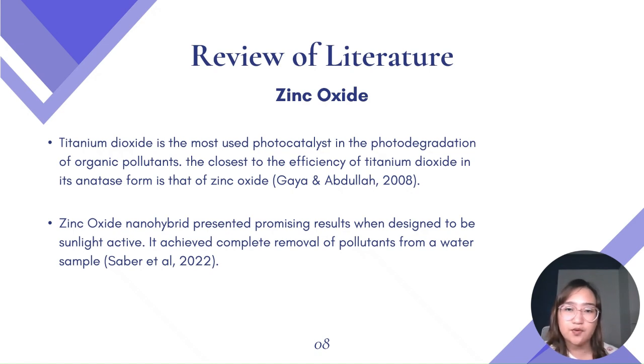Zinc oxide is observed to be of higher efficiency when its structure is crystalline and of smaller crystallite size and particle size. There are reports suggesting that the optimum size is in the range of 7 to 15 nanometers for various photocatalytic reactions. In another study, a zinc oxide nanohybrid shows promise when designed to be sunlight active. It achieved the complete removal of pollutants from a water sample. This result provides insight into the potential of zinc oxide as a viable photocatalyst comparable to titanium dioxide. This study aims to find the best alternative and contribute to the decades of research on photocatalytic degradation.